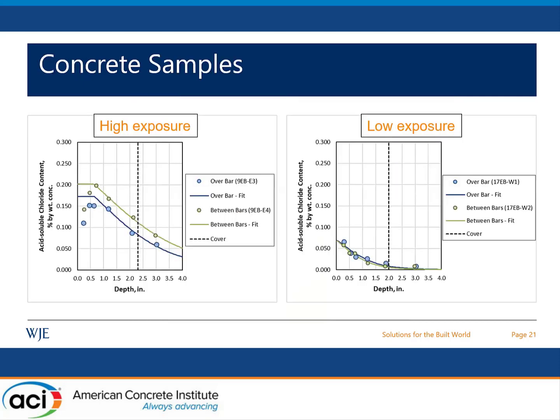We took a total of 36 concrete core samples from these areas and divided them into high exposure and low exposure categories. Using the chloride profiles that we obtained from each of these cores, we fitted diffusion coefficients and surface chloride estimations to these cores to get an estimate of what the concrete's diffusion characteristics are and also what the average exposure conditions are in these two areas.